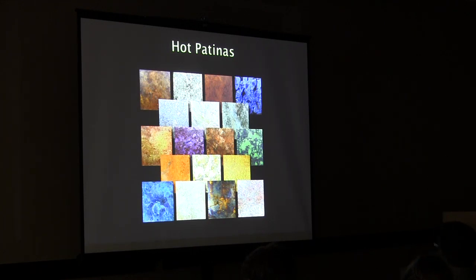This is where I've done a red granite underneath, and that's done with a spray bottle with droplets at about 200 degrees, so the droplets stop. And this is 5 different patinas to get this red granite. And over the top of that, I took a sponge and I diluted titanium dioxide white 50%. With a sponge, I made all these veins.